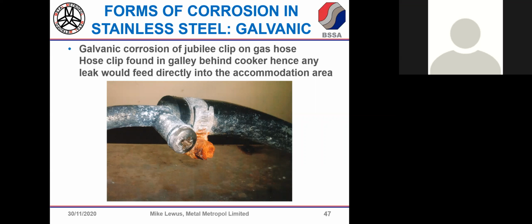Simple maintenance can solve a lot of problems. Washing things off, checking if there's any sign of degradation. If you've chosen a cheaper material, at least be ready to replace it. Interestingly, there's what looks to be a stainless steel head there next to the heavily corroded nut on the Jubilee clip. And obviously that's getting covered with debris. You can even see the beginnings of tarnishing on the inside of that. But it looks a little bit of a horrible situation to me. And it's certainly something you'd want to take the right measures to avoid, I think.